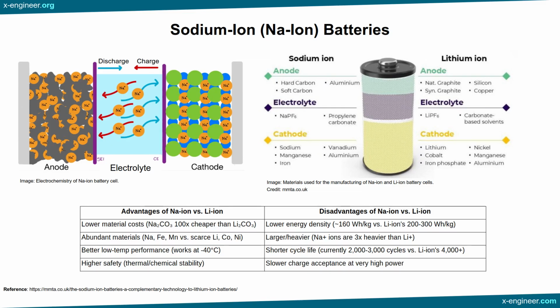A key advantage lies in material sustainability. Sodium-ion batteries eliminate dependence on scarce lithium, cobalt, and nickel, instead using globally abundant materials: iron and manganese in cathodes, hard carbon, from biomass or petroleum byproducts, in anodes, and aluminum current collectors instead of copper. Sodium carbonate, the primary raw material, costs 100 times less than lithium carbonate. This not only improves supply chain resilience but also reduces geopolitical risks associated with critical mineral sourcing.